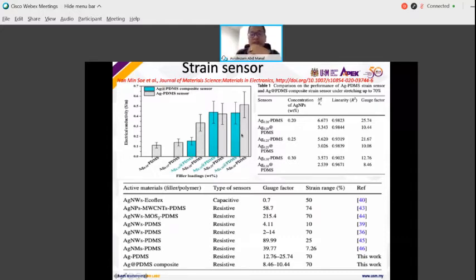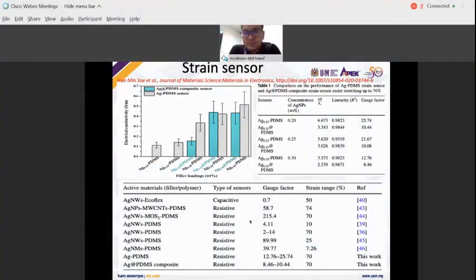Of course, if we increase the silver nanoparticle percentage, it will also increase the conductivity of the ink, right? So we tried a few formulations, and came to the 25 and 20. With the 25, we can do testing on the strain sensors. We tested on finger movement, and then we do the analysis of what is the maximum strain. So that is one example of the strain sensor fabrication in our group.